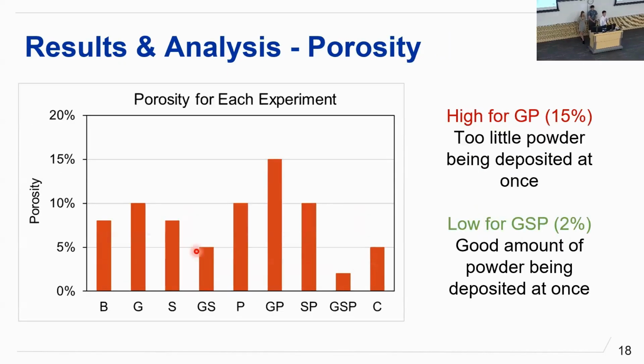Next, we have our porosity measurements. We found a very high porosity for experiment GP, and we attributed this to the fact that there was not enough powder being deposited at once. There wasn't enough exposure on any given area of substrate at some time, so it couldn't condense. And we had a very low porosity for experiment GSP. We found that there was enough exposure of the substrate to the nozzle so that the powder could condense and form that anchor layer.